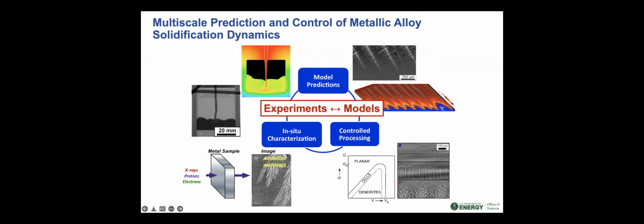So shown here on the top right, we have an example of synchrotron X-ray imaging of a dendritic array in an aluminum copper alloy that we've obtained. And then down below is a complementary 3D dendritic needle network modeling simulation of that array evolving at the micro-mesoscale. And then on the left, we have an example of 800 MeV proton radiography that was performed of a casting mold filling at the macro scale. And this was done at Los Alamos National Laboratory's PRAD facility. And then coupled with that is a continuum scale simulation.